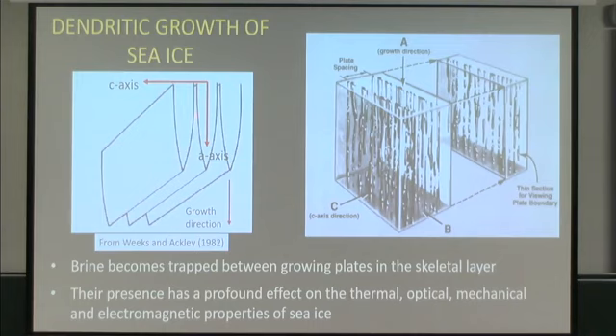So you actually have these blades. The C-axes are normal to these plates, and the plates grow out, and in the regions in between the plates, they trap liquid brine, and that stays in the material as the growth proceeds. So, a little drawing here, you have a few of these boundaries. If you're having trouble visualizing this, if you have kids or grandkids, picture your kid with a jar of jelly, and they go grab your favorite book off the shelf, and they go through your favorite book and they smear jelly down each page, and then close the book back up and put it on the shelf.